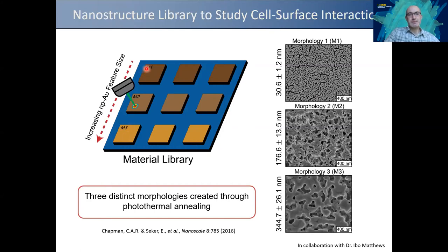And we microfabricated porous gold patches on a chip and used laser sintering to coarsen them to different morphologies. So now on a chip, almost similar to a DNA microarray, except instead of displaying DNAs with different sequences, you actually have materials with different morphologies on a single chip. So now you can have these identical chips, so you have repeatability in your experiments, and you can culture the cells on all of these cheap chips, fix them and stain them, and in high throughput identify what morphologies are more conducive to astrocyte growth.